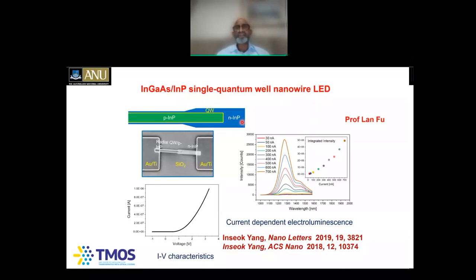Then he transferred them onto a glass slide and put some metal contacts with gold and titanium by electron beam lithography patterning. So now he injects current and looks at the voltage drop, or applies the voltage and looks for the current. You can see the IV characteristics showing diode-like behavior, showing that In Suk's hard work has paid off and he's able to make a PN junction and also make good contacts there as well. So now if you inject the current into these nanowire diodes, you can see that brighter light is coming out of these ones, and the higher the amount of current, the higher the light intensity which is coming out of these ones.